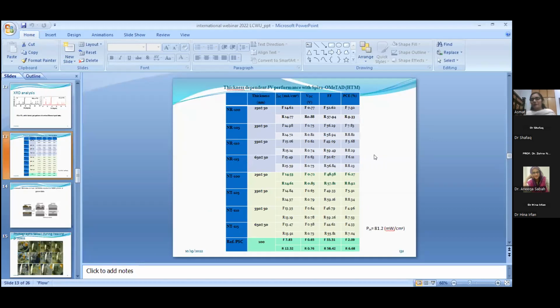Similarly, nanotubes were grown, and we can see that the efficiency is reduced with increasing thickness. You can see the efficiency is reduced with increasing thickness, and a similar trend we can obtain in the nanotubes as well. So we compare these results with our planar device. This is the reference perovskite solar cell with the planar device, and we can see that the efficiency is much less than our nanostructures.